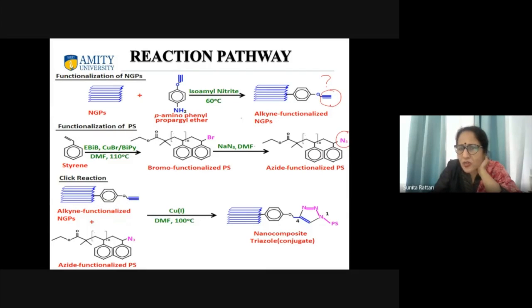So now it has got a very facile alkyne group here and azide group here. So two components are there. I'm not mixing them as such, right? When I mix them, there should be a reaction between these two. And this is what exactly happened when I mixed these two, this reaction happened, and this polystyrene, which is a polymer, was linked to the graphene through this triazole linkage, right? So what I got out of this,